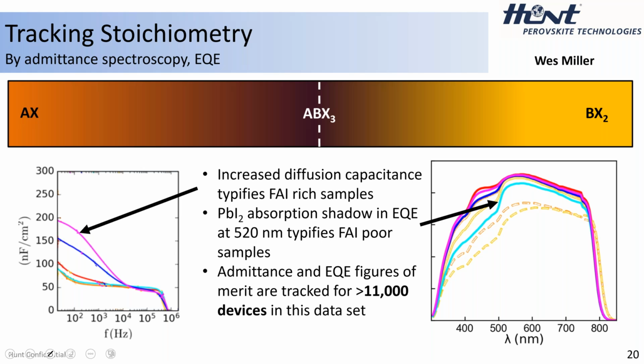So there's two things we've been able to come to understand. First is that if you have a super stoichiometric film, as represented here as a swing to the left, we actually get a relatively high low frequency capacitance, say close to 200 nanofarads per centimeter squared by admittance spectroscopy, whereas a good functioning cell in our case, what we believe is stoichiometric material, is closer to 100 down here. So we believe this is related to this, and this is related to this, or probably maybe somewhere in the middle. Can't go too crazy. So if you have too much AX of the ABX3 structure, you get this high low frequency capacitance. If it's stoichiometric, you get a lower one.